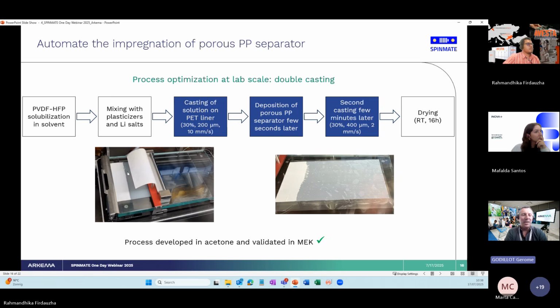So what we did here is first cast on a PET liner the solution of PVDF-HFP, plasticizer, and lithium salt, and just a few seconds later deposit on top of this first layer, still wet, the porous polypropylene separator, in order to impregnate at least the bottom half of it. And then less than a few minutes later, we cast on top of this porous PP separator a second layer of the solution to impregnate the top half of it, with extra solution on both sides of the porous PP separator.